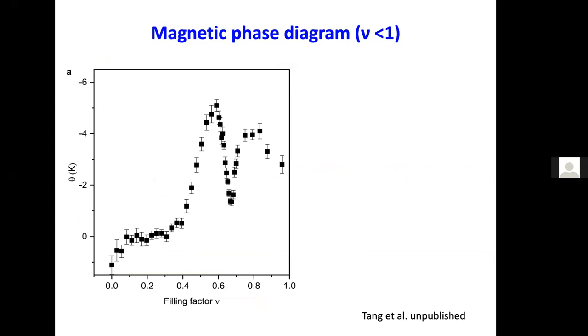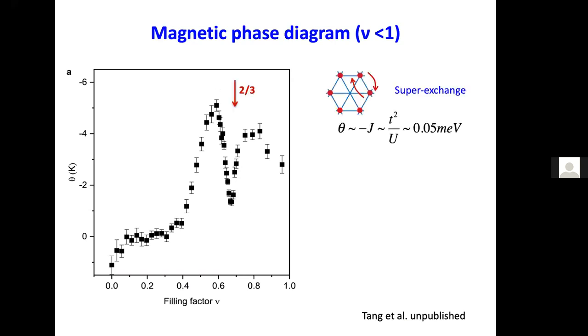Yeah. So our current understanding is that the charge ordering competes with the antiferromagnetic exchange, and that's why the antiferromagnetic interaction, the exchange energy, is low at this particular filling, two-thirds. Because there you just get the nearest neighbor contribution, because all the charges are pinned down, right?